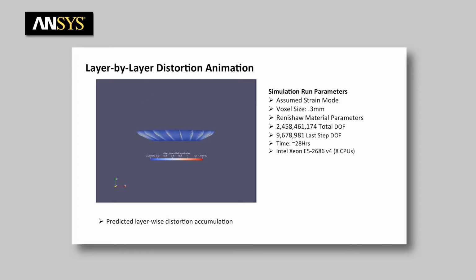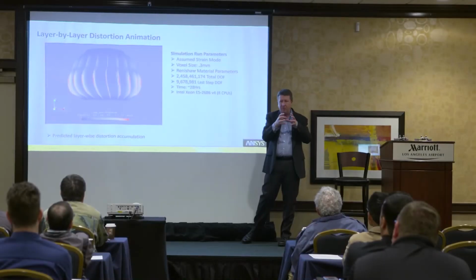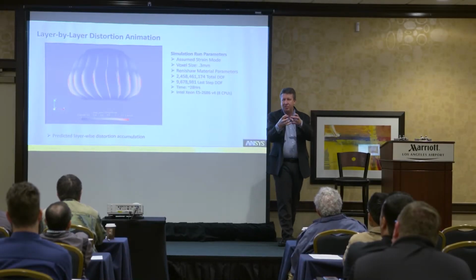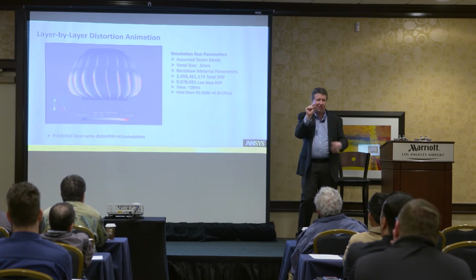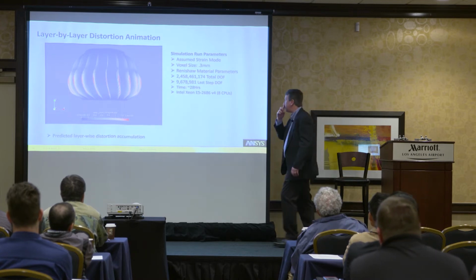And you see that it starts out relatively accurate, but as the blade continues to be built, this lower region distorts more and more and more, and over time goes way outside of any tolerancing you'd have on that blade. And so this simulation, we ran it at 300 micron voxel spacing. That's basically the nodal distances in the solver. We basically just decompose the geometry into little cubes, and voxel is the size of your cube.